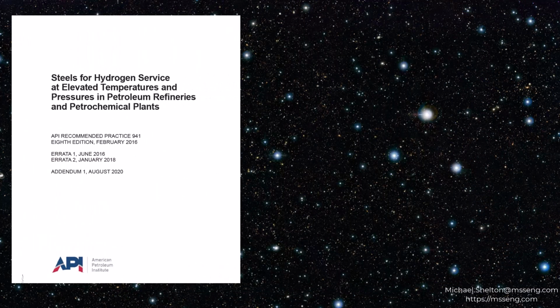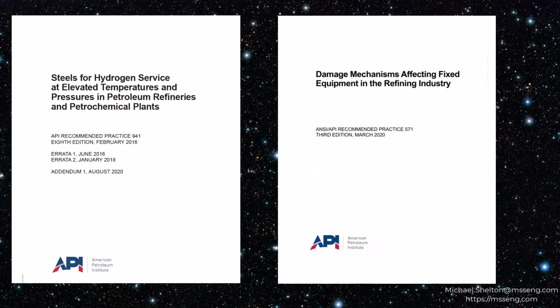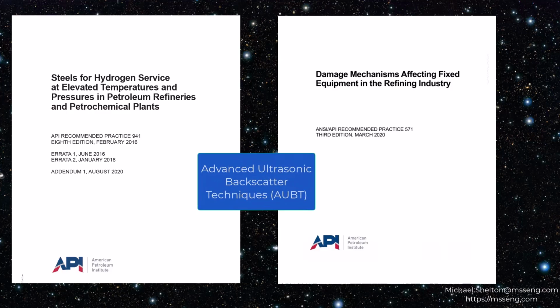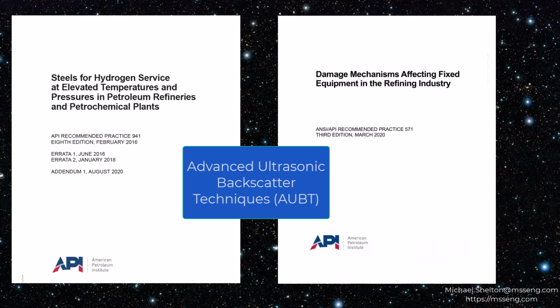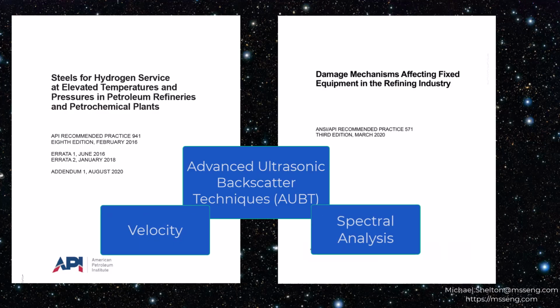Both API 941, steels for hydrogen service at elevated temperatures and pressures in petroleum refineries and petrochemical plants, and API 571, damage mechanisms affecting fixed equipment in the refining industry, deal with inspection for HTHA. Advanced ultrasonic backscatter techniques, AUBT, have proven the most successful. Usually the backscatter method, depth of damage, is further refined with velocity ratio and spectral analysis for backscatter result confirmation.